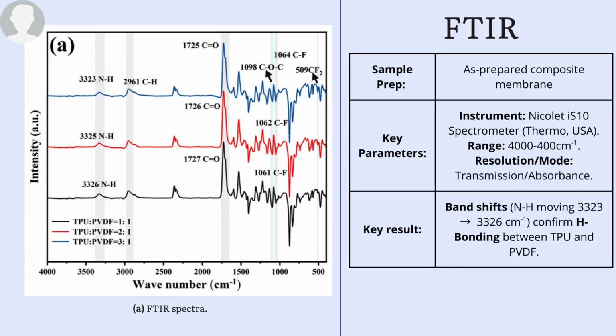This analysis focuses on band shifts rather than just band presence, as these indicate intermolecular interactions. Specifically, looking at the nitrogen-hydrogen stretching band at 3,323 inverse centimeters, and the carbonyl, carbon double bonded with oxygen, band at 1,725 inverse centimeters, distinct changes are visible. In the composite material, these bands shift to slightly higher wave numbers, by 2 or 3 wave numbers respectively.